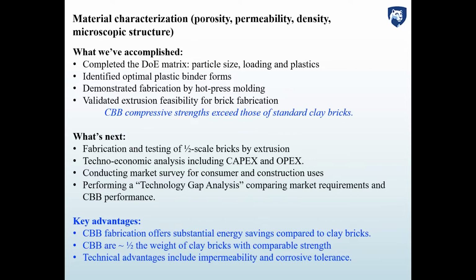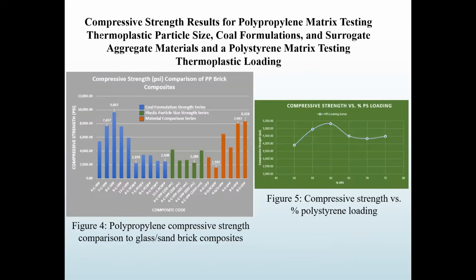The best part about this is coal-based bricks and blocks. We've exceeded the compressive strength relative to the standards of conventional clay bricks. So a conventional clay brick has a compressive strength of 6,700 PSI. And if I go back to this graph, this is just one series. We've made 100 or more bricks at this point with different thermoplastic binders. But you can see right here that there's 3 or more coal brick formulations that have exceeded the 6,700 mark.